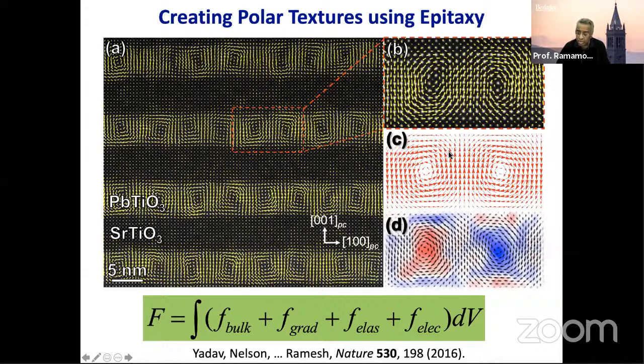And these are theoretical calculations, phase field calculations, which use this Hamiltonian, which has, of course, the Landau bulk energy, the gradient energy. The two terms that are very important are the elastic and the electrostatic energy. As you can see in the bottom picture, this is exactly this vortex array. But you could see that the color you see there is the curl of the displacement. And therefore, it's telling you that as you get closer and closer to the center of the vortex, the curl, which is del cross P, with P being the order parameter, is getting stronger and stronger. Very much like a hurricane, okay? And as you go closer and closer, it starts to spin faster. Very much, except there it is the velocity vector. Here it is not the velocity vector, but it's really the dipole moment which is rotating.